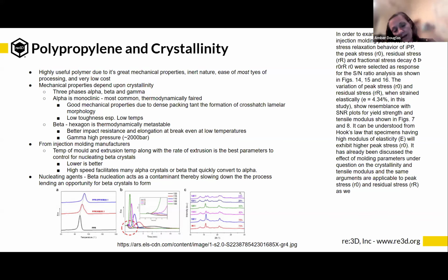But if you have it too high, you have crystals that are forming, you just can't see it happening. And it still may stay clear and you still don't even know that it's happening. And then all of a sudden you look at it wrong or you breathe on it and it turns all white. And that means it's turned crystalline and it's not going to work for you anymore.